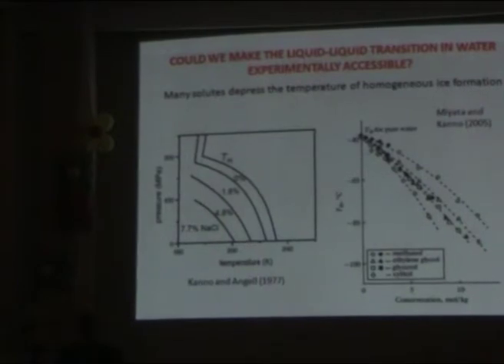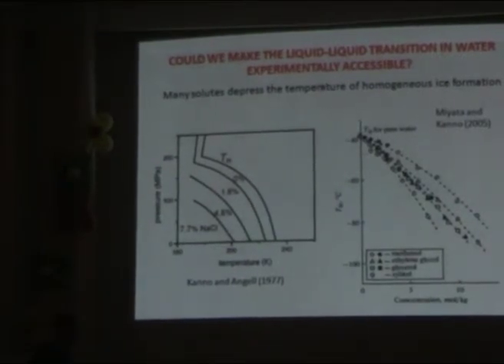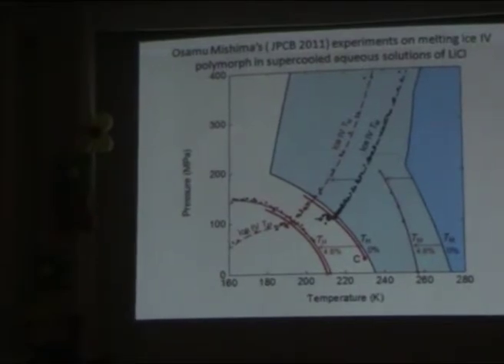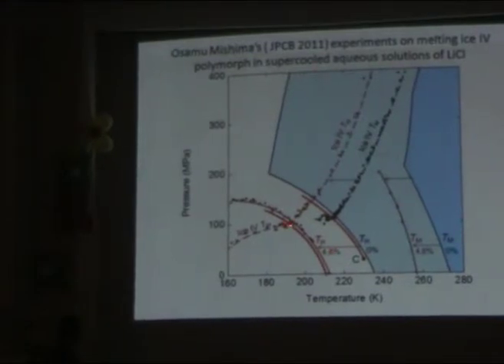In particular, there is a hope, because many experiments show that if you have a solute like salts or organic solutes, the line of homogeneous ice formation shifts to low temperature, and probably we could access a closer neighborhood of the phase transition. Next slide, please. There is some evidence, again from Mishima, from lithium chloride, that it could be the same story for the solution, 5% of lithium chloride, with the possibility of a liquid-liquid phase transition in aqueous solutions of salt. Next slide,